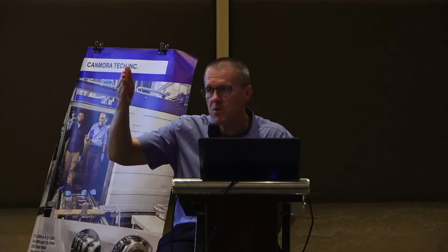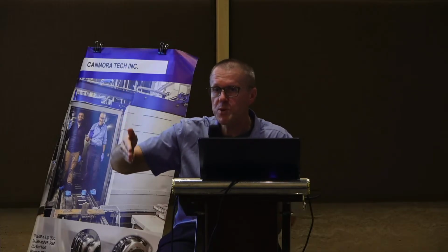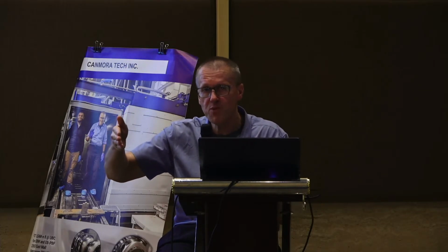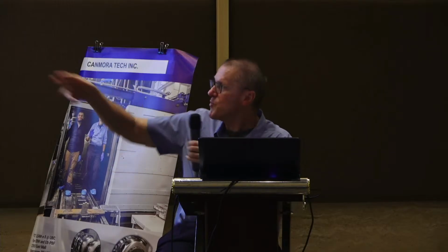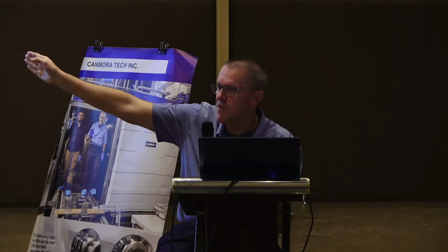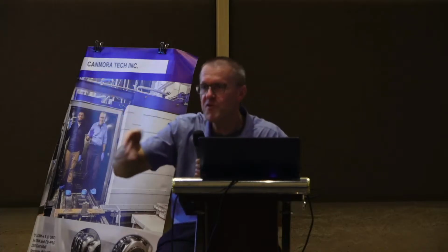At least you can find the sweet spot, right? So we said, okay, we want to optimize our process and find the sweet spot of the melt pool, and it could be either one of those, right? So you can have either the left or the right, but you have to fix one angle. You cannot just constantly change the angle with the galvos.